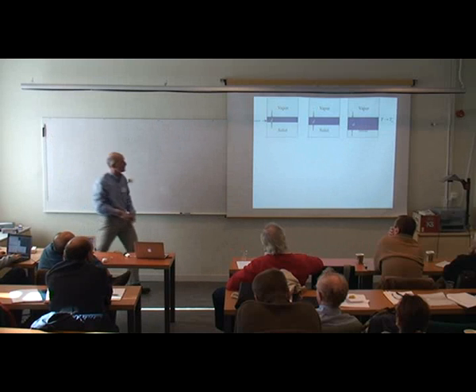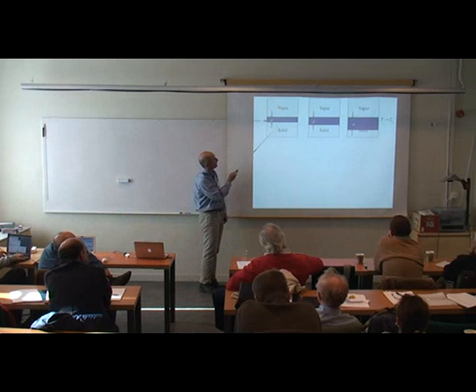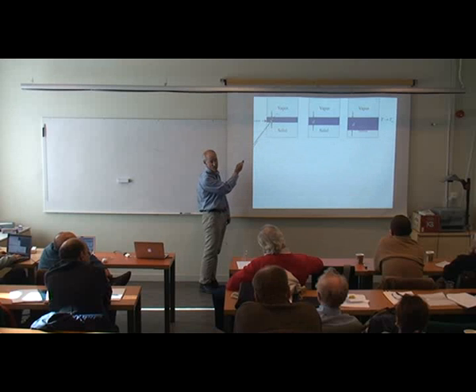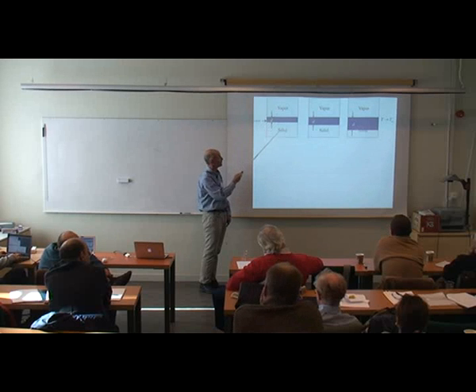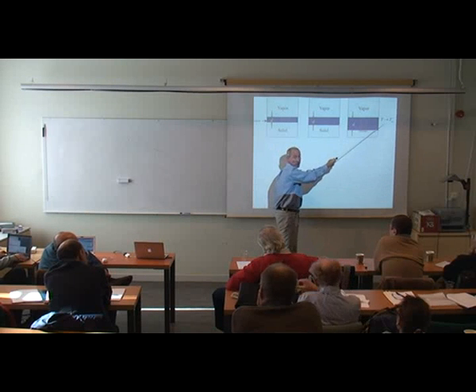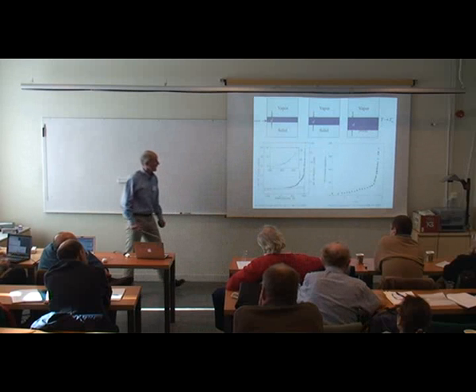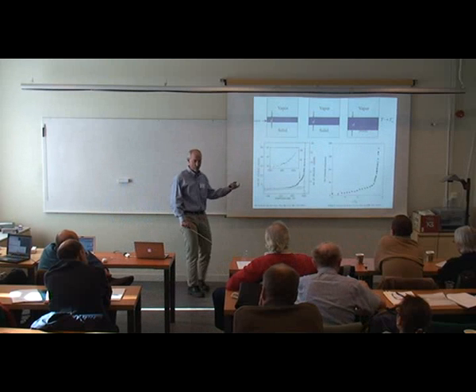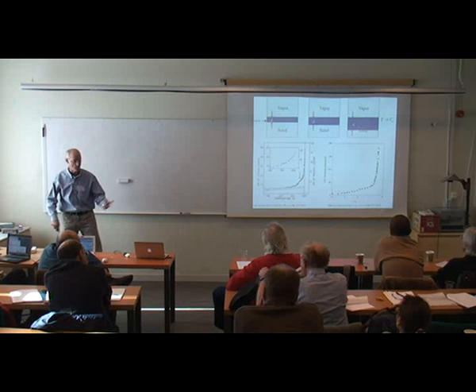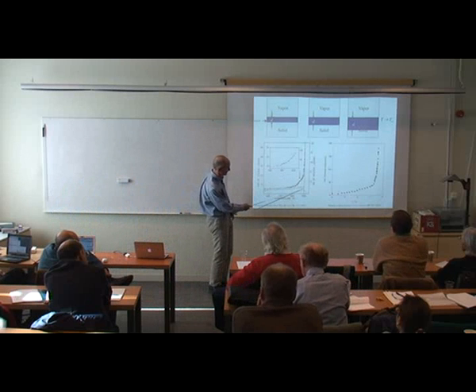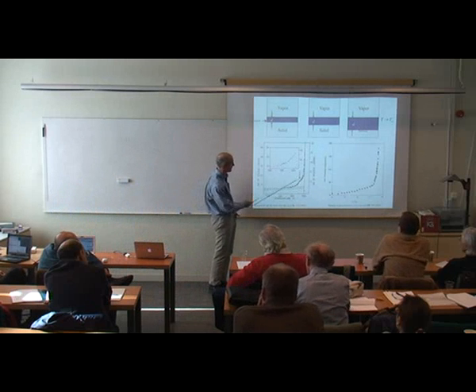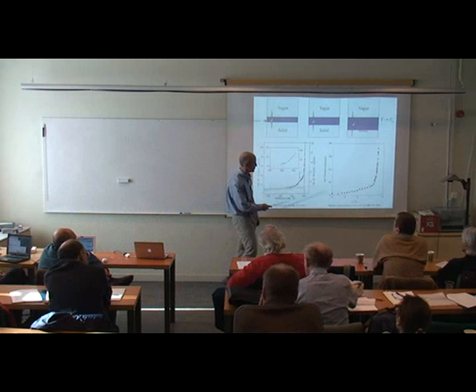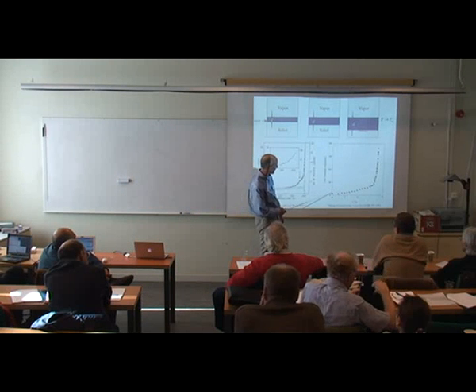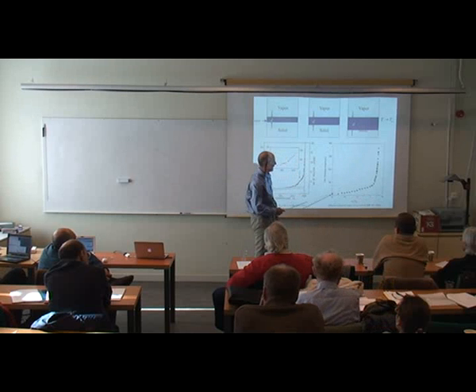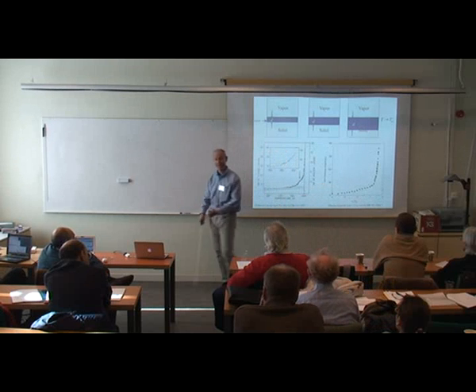And then when you get near the triple point, you will see a thin film of this material disjoining it from its vapor. Okay? Water at the interface between, say, solid and vapor. And that will grow as you approach the melting temperature from below. And this is observed in metals, rare gas solids, molecular solids, including ice, quantum solids, and so forth. Here's lead melting at 600 degrees, looked at by ion backscattering, a number of molten layers diverging. This is Michael Elbaum's thesis on ice. That's 0 degrees. You see hundreds of angstroms of water at the interface between ice and the vapor.